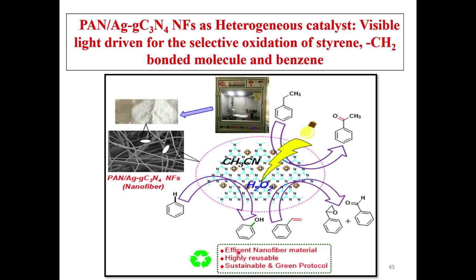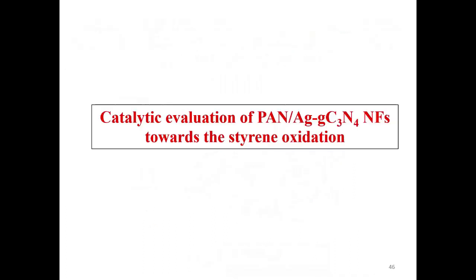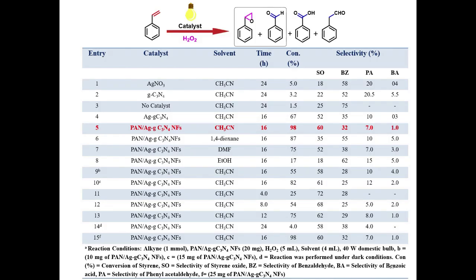They form these products. Which one is major, which one is minor, which one is selective, is determined with the help of this particular nanofiber. Now the catalytic evaluation of PAN-Ag-gC3N4 nanofiber towards styrene. Here is the styrene under light, with PAN-Ag-gC3N4 nanofiber as catalyst and H2O2 as oxidizing agent, and they form four products.